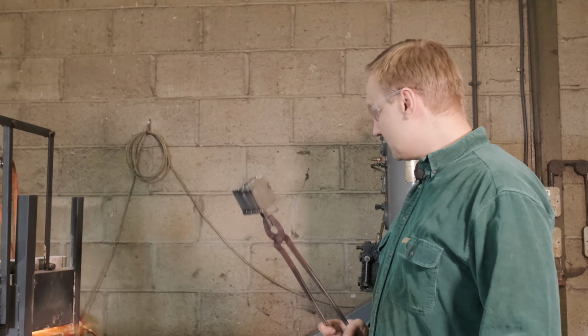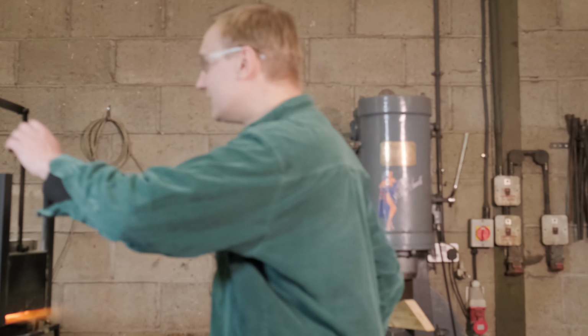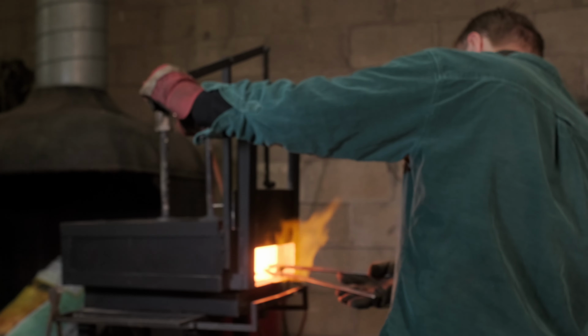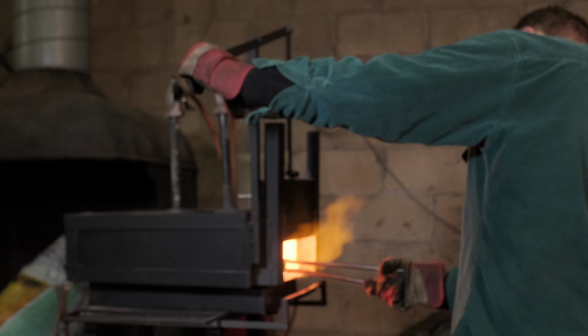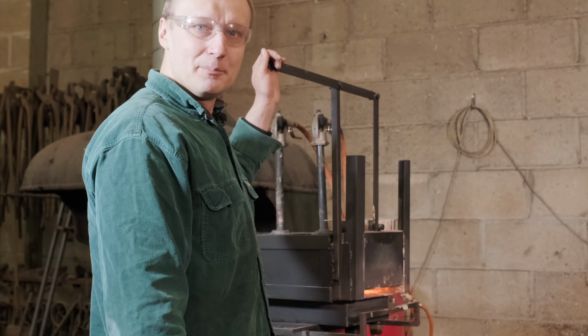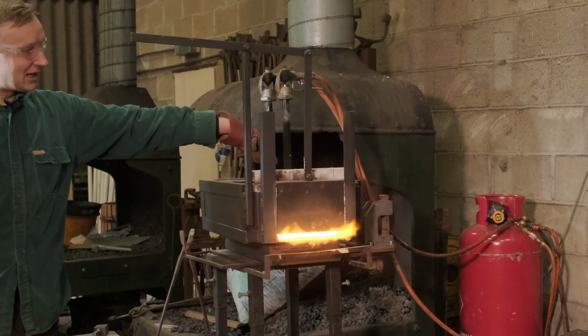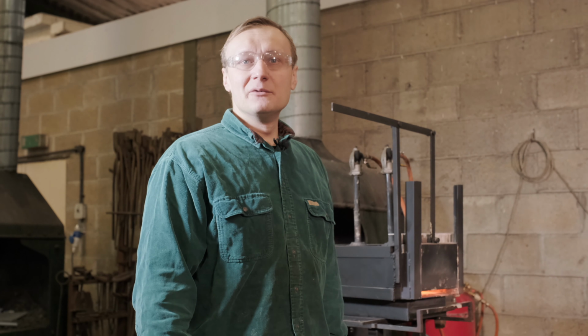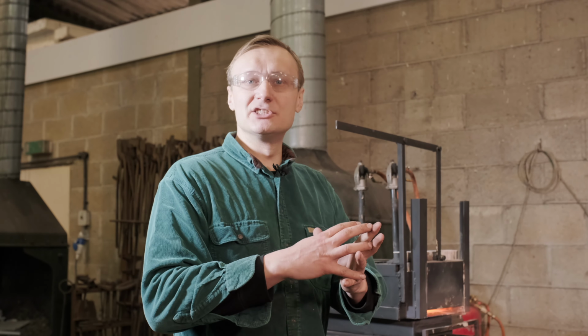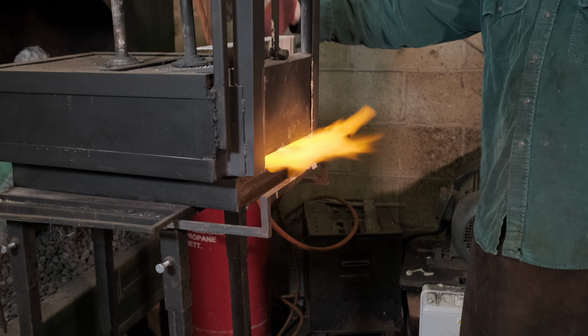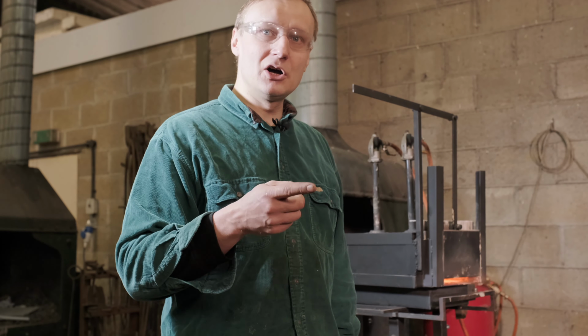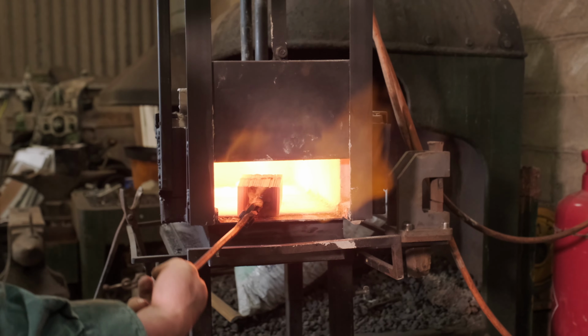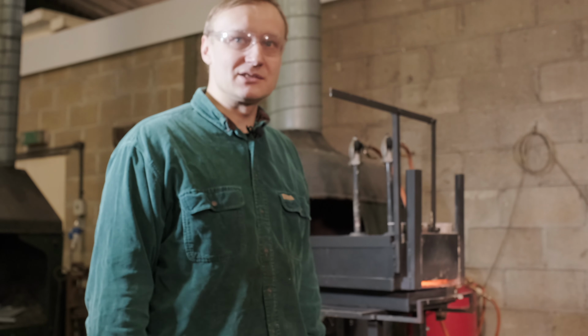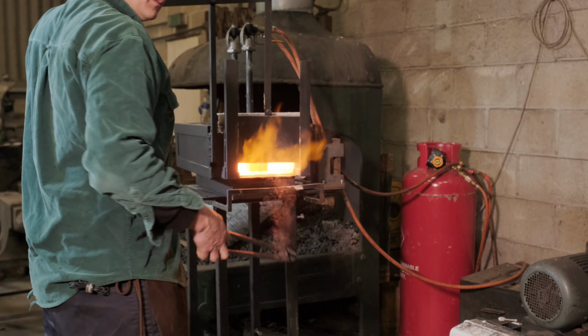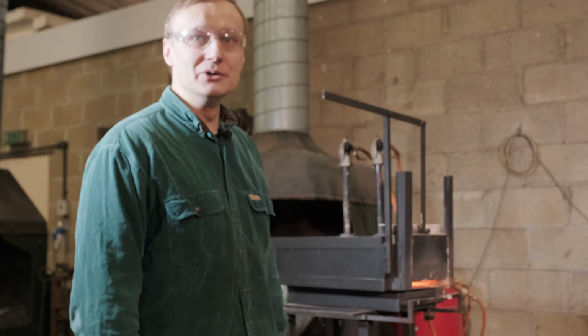All right, so forge is getting to temperature. It's hot enough in there to put our stack in. So I'm just gonna pop it in there and let it suck up the heat up to welding temperature, which is about 1000 degrees, 1100. And yeah, we let it suck up the heat. You want to make sure that the heat penetrates all the way through the steel. You don't want to take it out and start forging it too early, because even the outside might look hot enough, the inside might be still cold, and that will create problems in the future, cold shuts and other issues. So especially when you're working with the big stacks, take your time, let the steel get nice and hot before you do any forging with it.